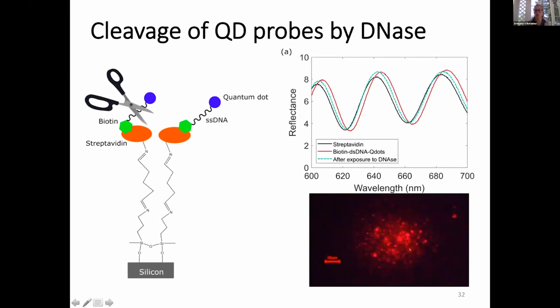In this case, we chose quantum dots because this provides another signal that you can measure independently. Because when you wash away all those cleaved quantum dots, you can collect them and look at how much fluorescent signal is coming from this mix. So similar to the testing done for PCR. But in principle, once it's used for calibration, this step will no longer be needed. You can just monitor the spectral shifts and get the information that way.